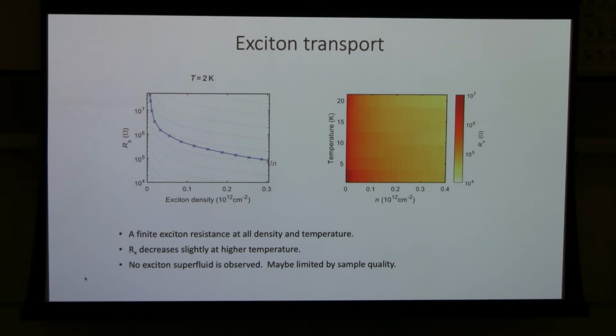So this measurement initially is very disappointing for us. We are really looking for an exciton condensate, where you should have very small exciton resistance, but we haven't observed it so far. Based on theory and on the exciton density and the temperature, if we have an ideal system, it should already be in the degenerate boson gas regime. So there should be some interesting Bose-Einstein condensation behavior. But the fact that we don't see it experimentally may be because our system still has too much disorder, it's not clean enough, and we are trying to make better samples to push this further.